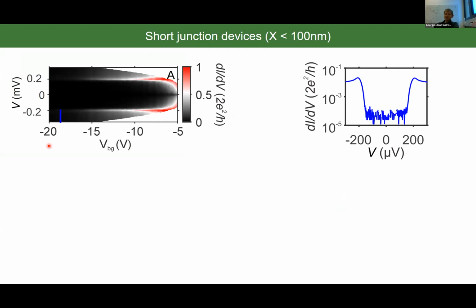As I already mentioned, the first thing we need to do is to find the proper gate voltage in order to adjust the transparency of our tunnel barrier. So what you see in this measurement, we measure differential conductance while sweeping the source drain voltage and stepping the backgate voltage. And you see that around minus 19 volts, you get a very hard gap. So the difference between the subgap conductance and the conductance above the gap is about 300. So that's the regime where we are going to stay in order to do our tunneling spectroscopy measurement.